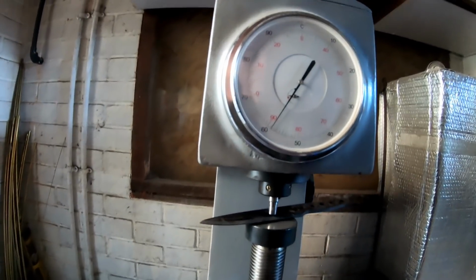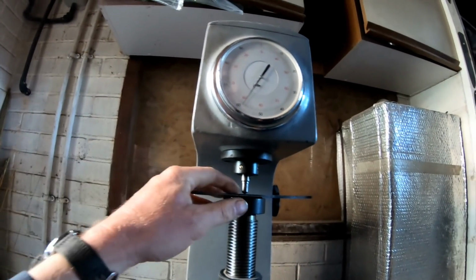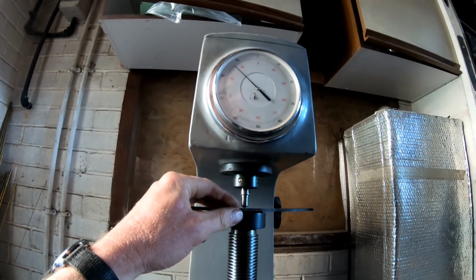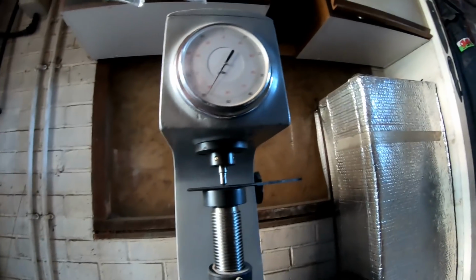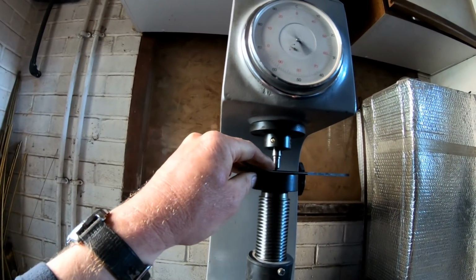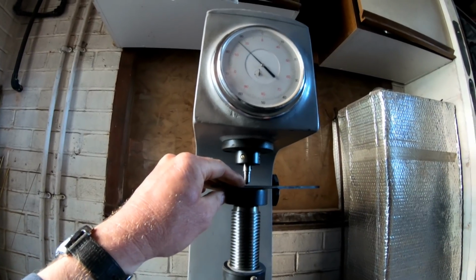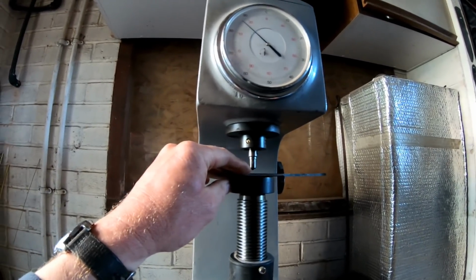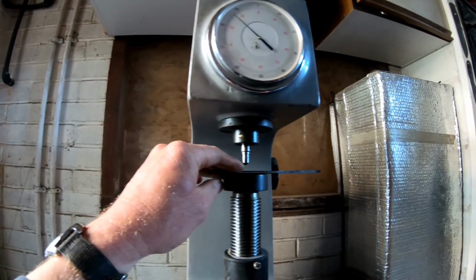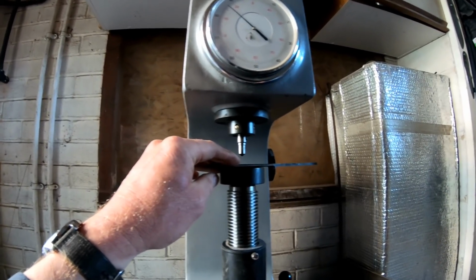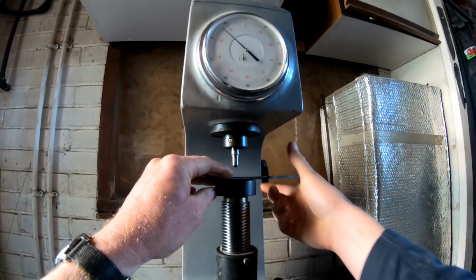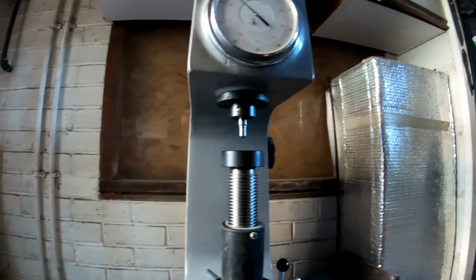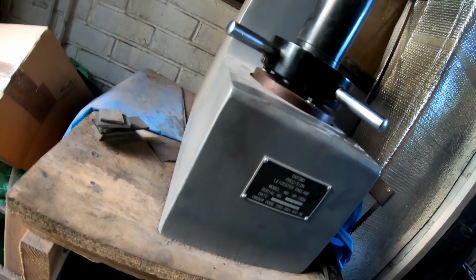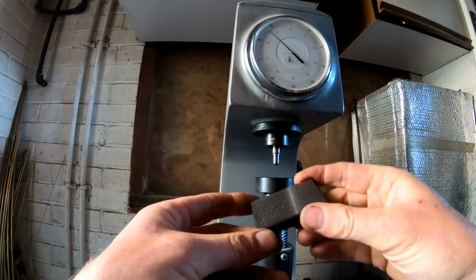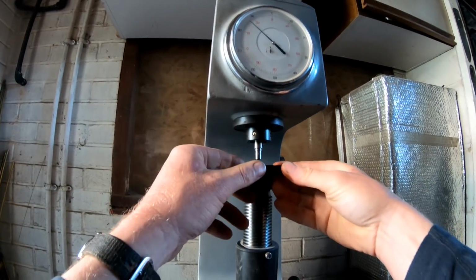So this machine measures to an accuracy of about 1/3 of a Rockwell point. What I like to do also on the Rockwell testing is do a comparison, because the machines, especially in this environment, I'm only in a workshop here. It's not a clean room environment. So I like to run a test piece, a test block. And I've got a test block here, and this gives me a comparison.